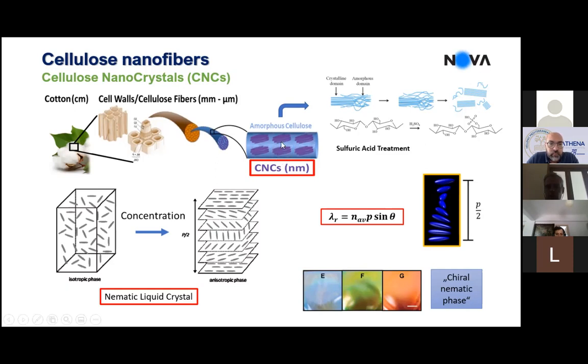If you make a suspension in water, like 3% of these nanocrystals in water, and dry the solution, they start to self-assemble in a way like you see here, like a liquid crystal. In one layer, you see the crystals aligned in one direction. They have a small rotation in the next plane, and this continues until they make the full rotation. So it's a kind of photonic crystal, and it has what we call structural colors. The color that you can get from these self-assembled membranes made of cellulose nanocrystals depends on the pitch of the rotation, and you can control this by the preparation of the cellulose nanocrystals.